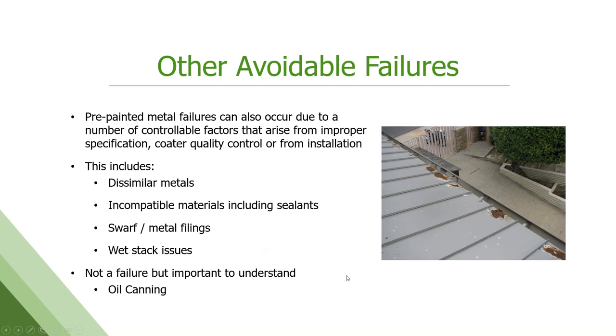Wet stack is corrosion that can occur when the panels are in the bundles on the ground still before they're installed. You get moisture in between them and it starts a corrosion process that can damage the paint finish.